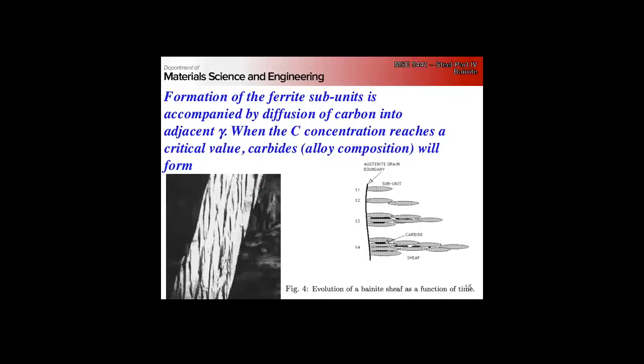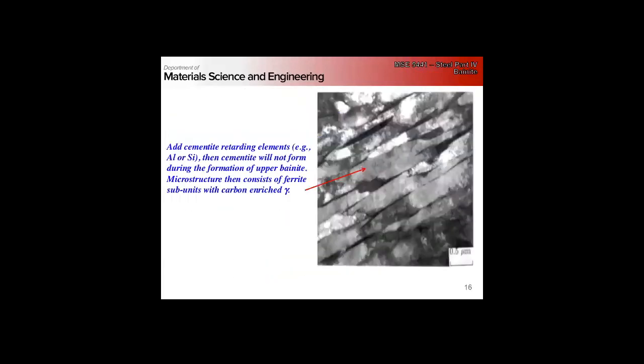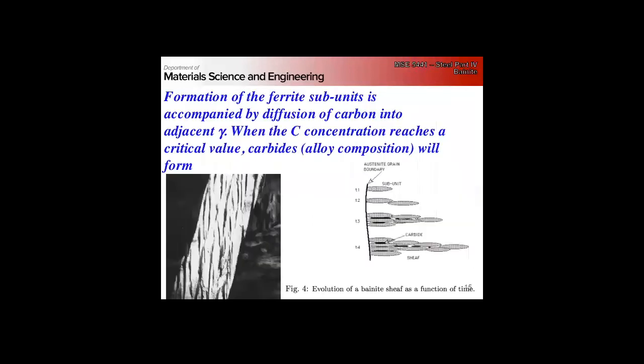And if we go up to the next slide here, right? So here we've got bainite without aluminum, with enough aluminum and silicon, we can suppress the carbide formation, right? And honestly, if you just had this picture, it's impossible to tell whether that's bainite or martensite, right? You've got nice, clean, what looks like nice, clean laths, right? And so without the carbide separation, there's so many similarities, except for the athermal nature of martensite,